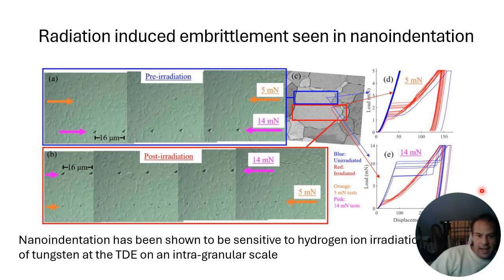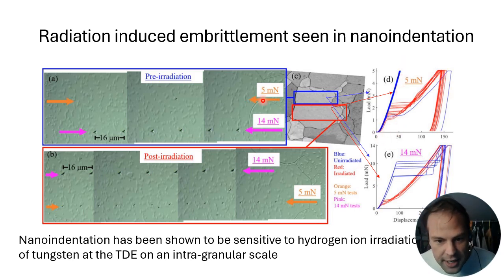Well, I do see this radiation-induced embrittlement. In this figure, there are 4 different colors. In blue, we've got unirradiated, and in red, we've got irradiated. Before irradiation, the tungsten exhibits a large, initially elastic response. You can load it up to 5 millinewtons, and there's no indentation impression left. It's just purely elastic loading. But after irradiation, you load it up to 5 millinewtons, and you can see every single indentation impression.